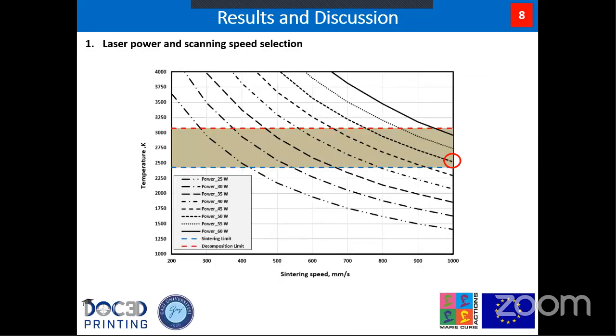We ran the model and obtained this figure, where you can see that different powers are used with different scanning strategies, and we obtained the range for the laser power and scanning speeds that can be used in SLS without any problems.